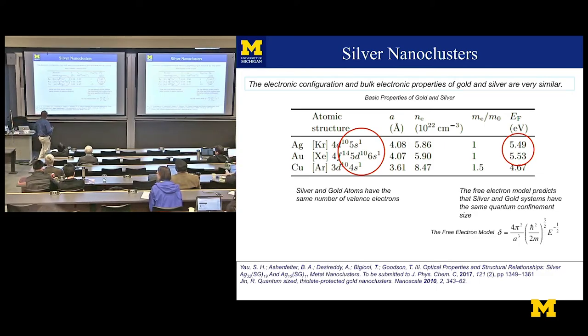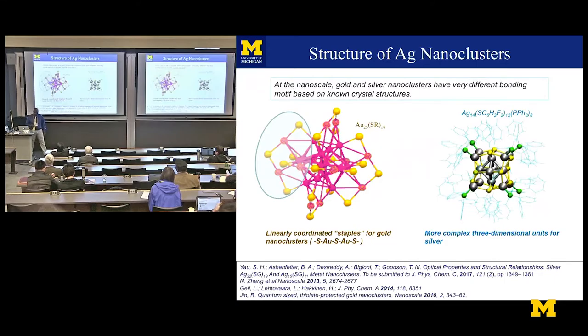However, you could use some free electron model to calculate how this very small distance really doesn't make that big an effect, but somehow people believe that the properties of gold and silver are different. So how different are they? Again, I go back to this interesting picture. It's all by Roger Kornberg, of the gold staple geometry. 13 atoms are in this pinkish color in the middle, and then the rest are in this staple geometry of gold, sulfur, gold. That's the geometry.